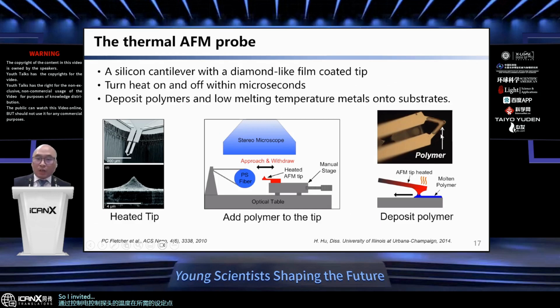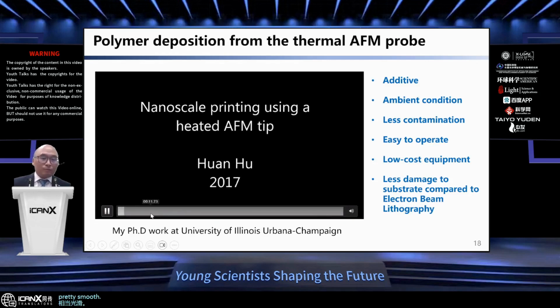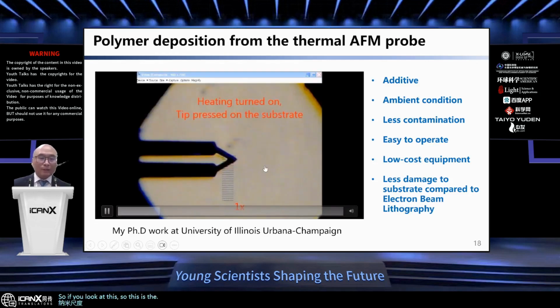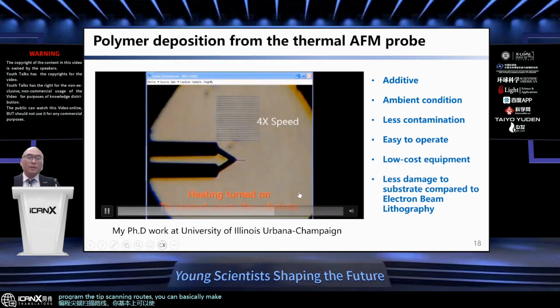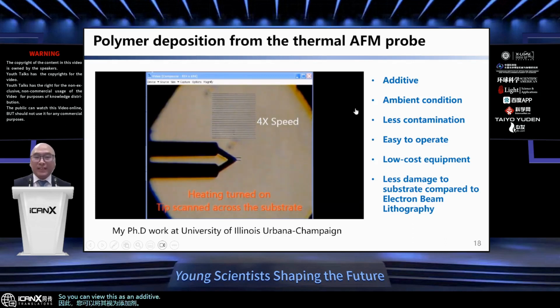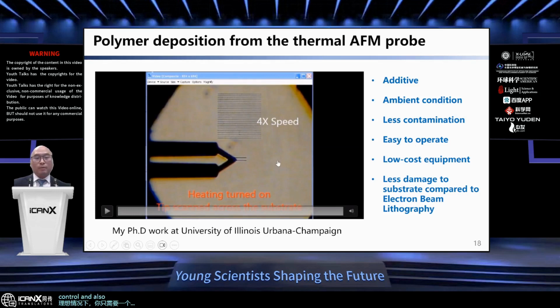So I invented a good method of inking this polymer on the thermal AFM probe. Then we can do pretty smooth nanoscale printing. If you look at this, this is from the back of the micro cantilever. You just need to program the tip scanning routes. You can basically produce arbitrary shapes of nano patterns of polymer. You can view this as an additive nano printing technique, and it works in ambient conditions. You just put the nano pattern wherever you want, and it's easy to operate. Ideally, you just need a stage control and also a thermal probe with control circuits. You can do nanofabrication.